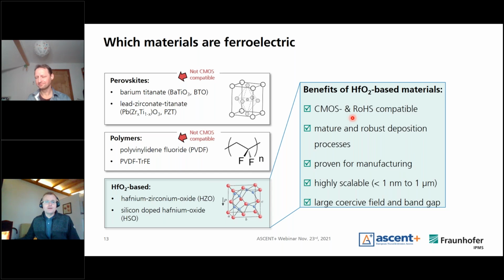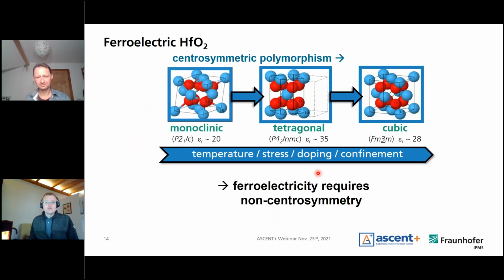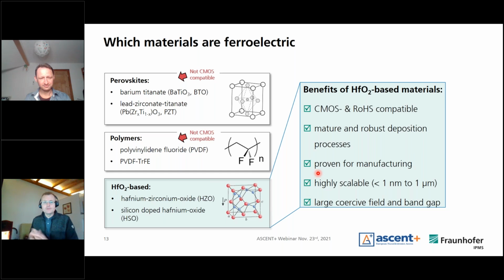So hafnium oxide is already established in CMOS fabrication, like high-k metal gate technologies, and also it's a quite mature and robust deposition process. It is scalable, so I also come back later to the thickness tuning, and it's already established with standard manufacturing tools. So hafnium oxide is used in transistors, but it has to be in a special state in order to be ferroelectric.